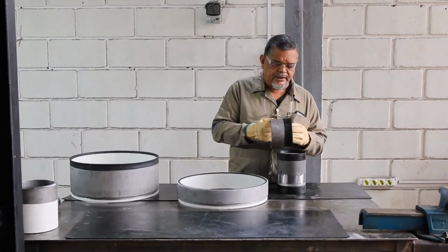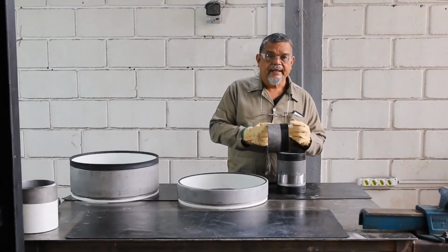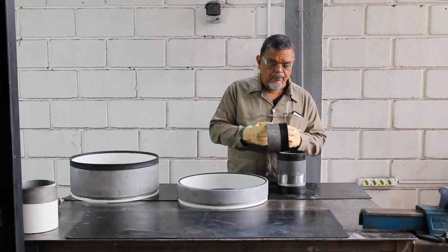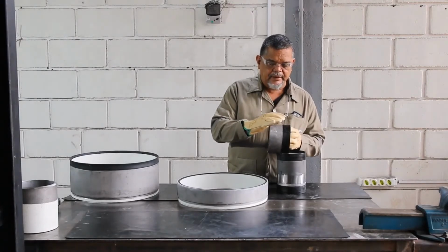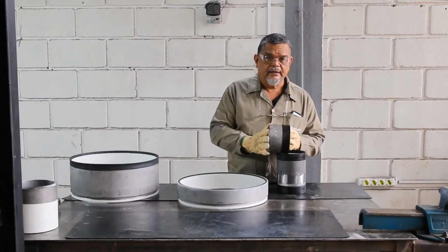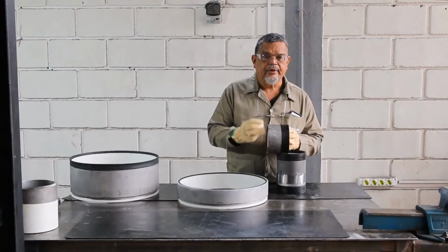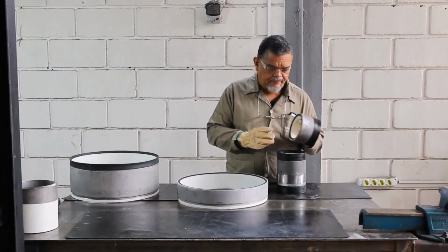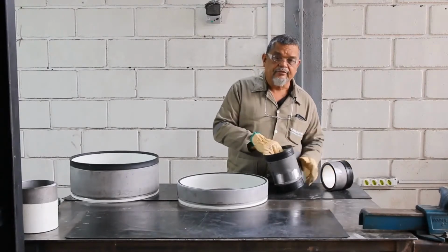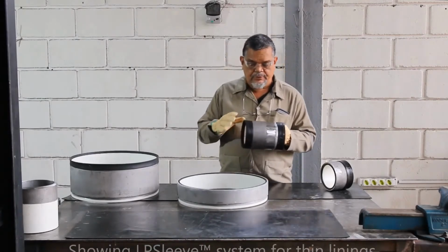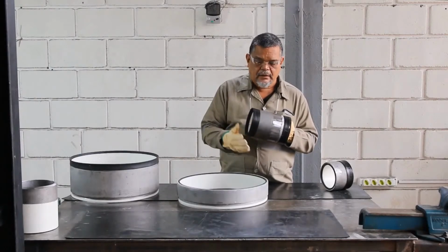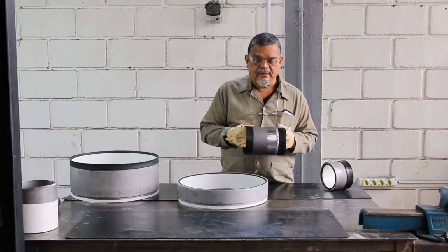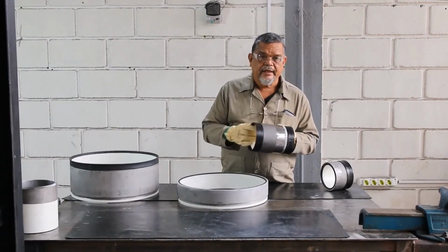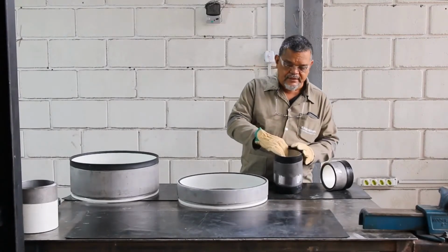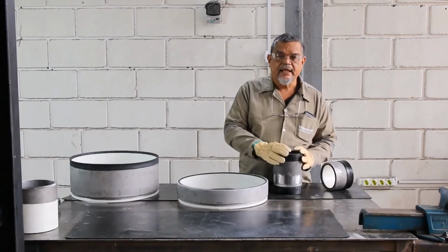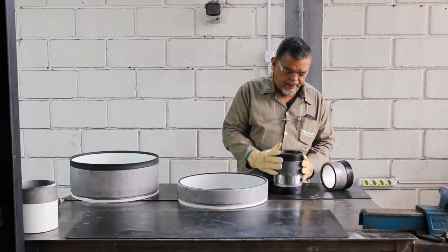We also have another seal, which is a bore seal, which seals the ring against the liner of the pipe that is welded. So the ring is completely sealed both in the back and in the front, preventing the fluid from getting in touch with the parent metal of the pipe. We also came out with a sleeve, which is based on the same principle. In other words, we have an insulation layer that prevents the heat of the weld from affecting the liner, and we have bore seals in both ends of the sleeve. Both the sleeve and the rings are lined with material which is the same or compatible with the material that lines the pipe.